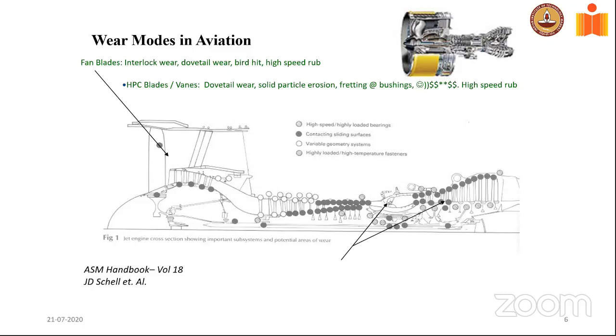This is a very busy slide, but what I really want to say is that all these black dots that you see represent what is called sliding and fretting wear. And then these open circles represent high-speed rubbing, which takes place at Mach 1 velocity. Then you have these bearings, which are high-speed, highly loaded bearings. Really sorry about the small font. And then you have fasteners, which can undergo fretting. In a very simple snapshot, this covers the entire spectrum of the kind of wear that would take place.